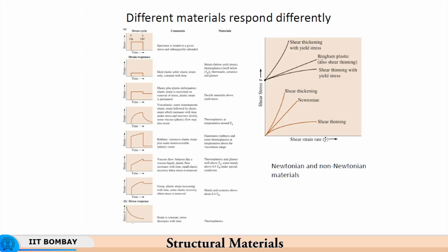So, the shear rate and viscosity are linked in that a higher shear rate would cause shear thickening in one type of materials and shear thinning in another type of materials. Typically polymers, thermoplastics which we use for injection molding for instance, show this shear thinning behavior, because as shear rate increases, the viscosity continues to decrease, whereas with Newtonian fluids the viscosity remains constant.